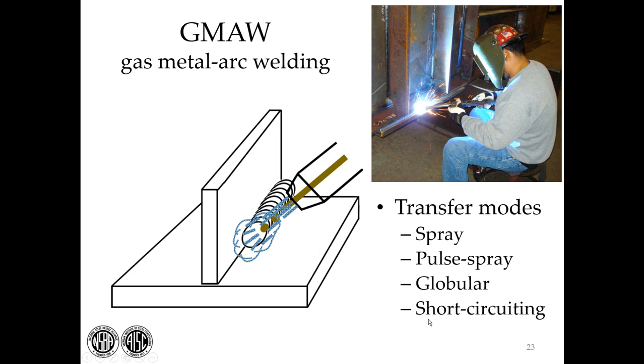Short-circuiting is a very low heat process intended for very thin materials. Consequently, it does not work for thick materials. The heat in a short-circuiting transfer is so low that it won't properly melt the base metal to create that fusion. And so, therefore, we do not allow short-circuiting in the bridge welding code, but it is very useful for thin materials. These other transfer modes are allowed, and the more common are these top two.